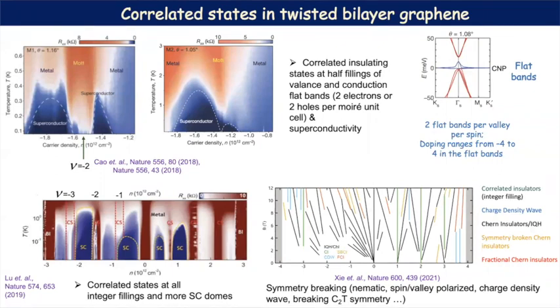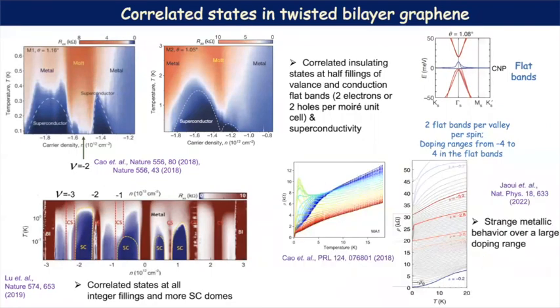And then in 2019, we saw that we can have insulating states at all the integer fillings in the phase diagram, and we have more superconductivity. And now we know from various experiments and theory that it's possible that we have many different kinds of symmetry breaking and topological phases in this system. And not just the insulating phase, but we also have a correlated metallic state, where you can see this strange metallic behavior of resistivity for a broad range of doping values, and the linearity goes down up until very small temperature, which is of the order of millikelvin.